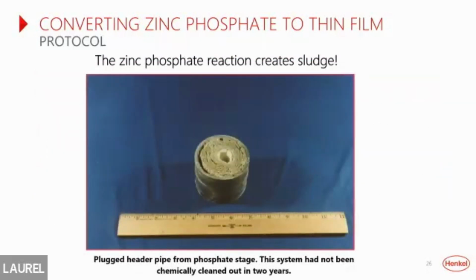Here is a great example of a phosphate header pipe, a 3-inch header pipe in a system that had not been cleaned out in 2 years. And that buildup in there is zinc phosphate sludge. It reduced the opening to about 1/2 inch. Now, at this point, even a chemical boil out is not going to remove that. The pipes are going to have to be removed and replaced.